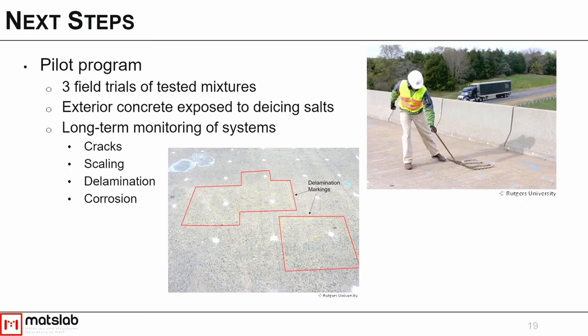Basically, we're going to do 3 different field trials of tested mixtures. It's all going to be exterior concrete that's exposed to de-icing salts, exposed to freeze-thaw cycles. We're going to do long-term monitoring of these systems. So we'll do crack mapping, look at scaling and delaminations, and also corrosion in these systems.